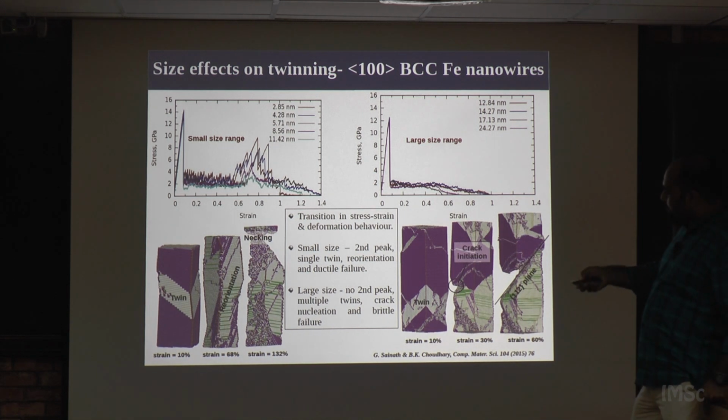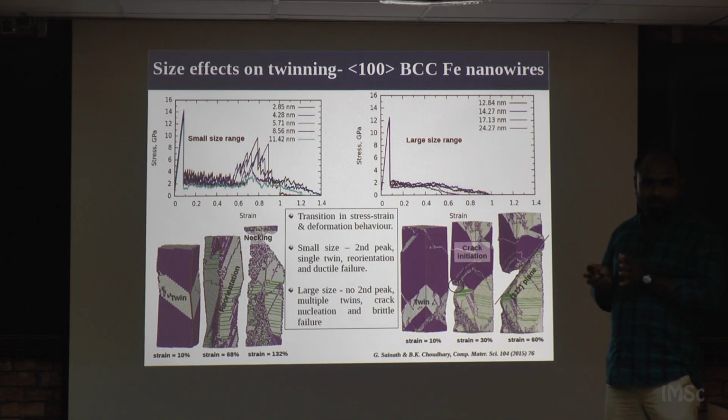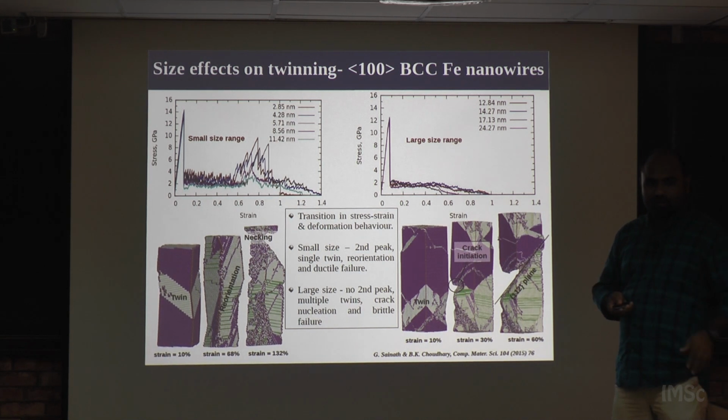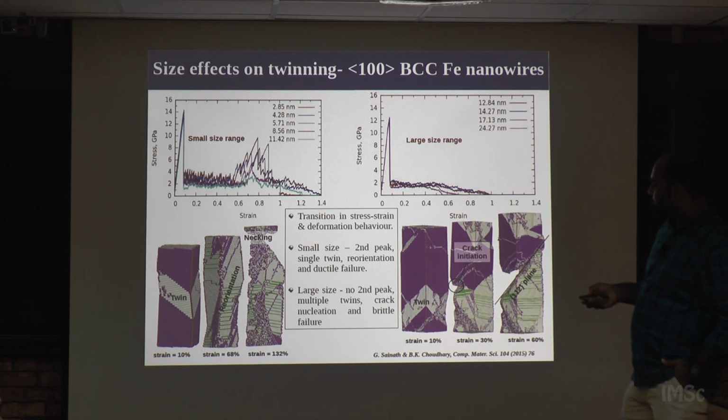That is again basically because the defect density increases. So, you can get a more average behavior in large size because of the larger number of defects, so less fluctuations, whereas in small size there are only a few, one or two. So, this behavior is very typical of nanowires. Yes, the nano part of that. Yes.